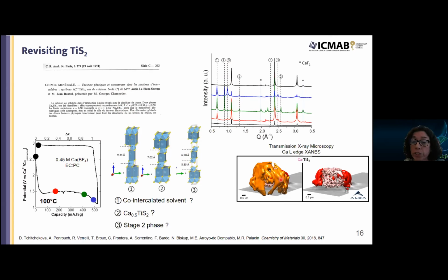This orange shell has a similar calcium density as calcium carboxylate, so it's likely produced by electrolyte decomposition. In red, this would correspond to calcium fluoride, which we also see on diffraction, also due to electrolyte decomposition. But then these pink bubbles would indeed correspond to calcium inside the TiS2 particles. Of course, polarization is huge, and as I was telling you, calcium anodes are not the best.